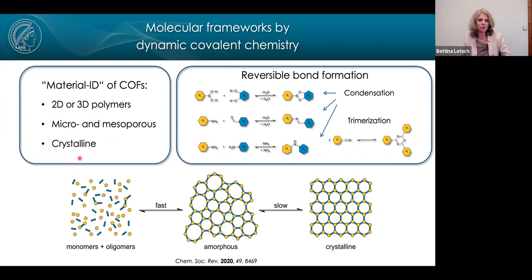So how can we make polymers crystalline? Basically what we do is we use reversible bond formation, so typically condensation reactions. And to keep up this reversibility, we need to make sure that the reverse reaction, hydrolysis or ammonolysis, can also take place. And so what this does is it gives us a mechanism of error correction. So we can close and reopen bonds close to thermodynamic equilibrium. And that will then help us to reach this ordered crystalline state in these polymers.